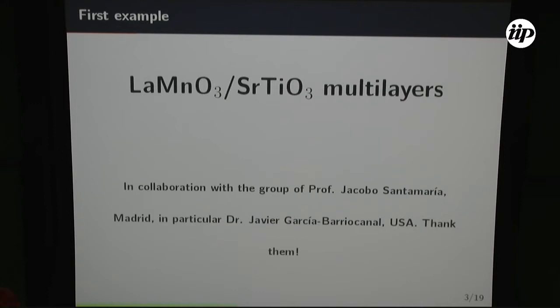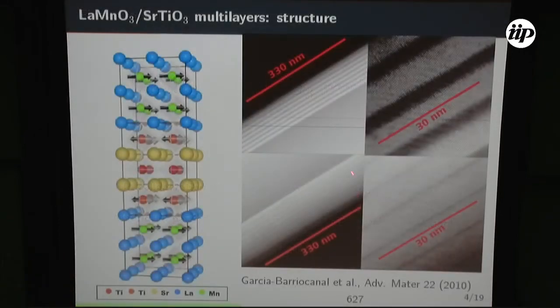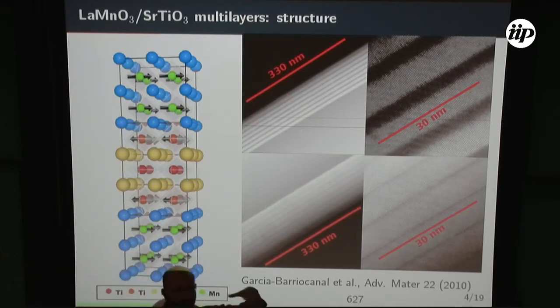notice how strong this technique is in this system, a heterostructure of lanthanum manganite and strontium titanate. This was done in collaboration with people from Spain, and they grew very nicely heterostructures where they changed the number of unit cells of the manganite, keeping always 2 cells of strontium titanate. So I'm not going to go into detail, but doing like that, they have samples with different magnetic and transport properties. Then the question was, what is the relationship between the macroscopic behavior and the atomic organization at the interface.